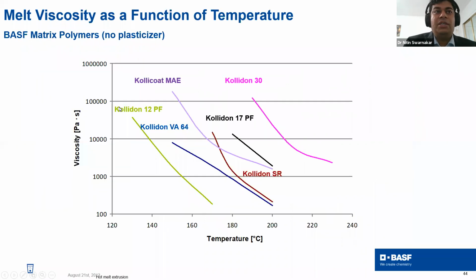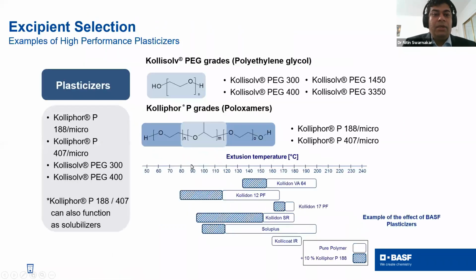Now coming to how the polymer looks, which I was talking about. Once you increase the temperature, their viscosity is going to decrease. As we know, when viscosity is lower, we can operate the instrument more efficiently. So this is how the overall polymer looks. Kollidon 30, you can see on the higher side, needs a much higher temperature, but VA64 is excellent. You can see how the viscosity decreases, which is very good for HME work.